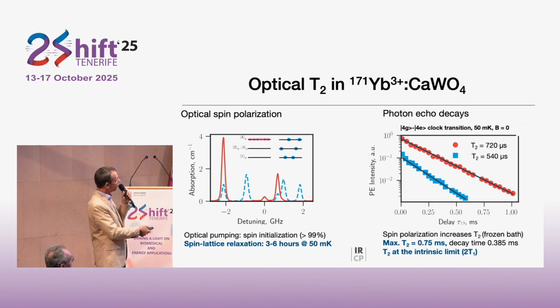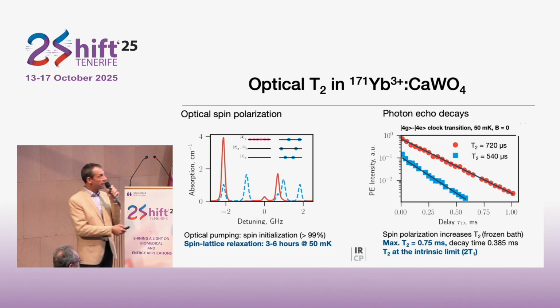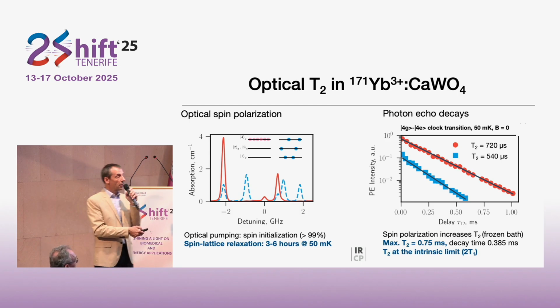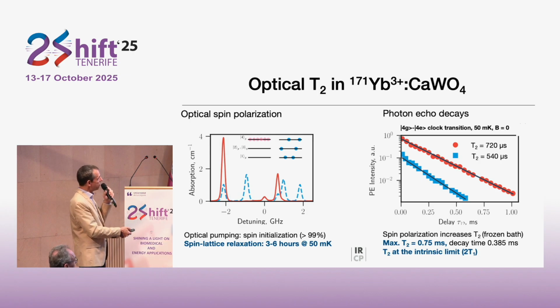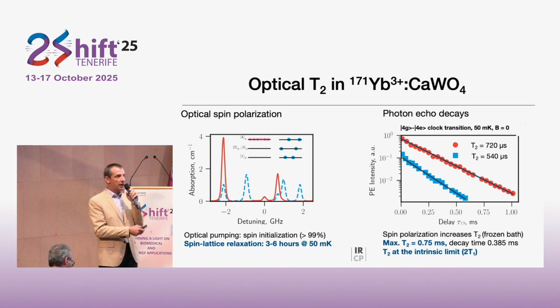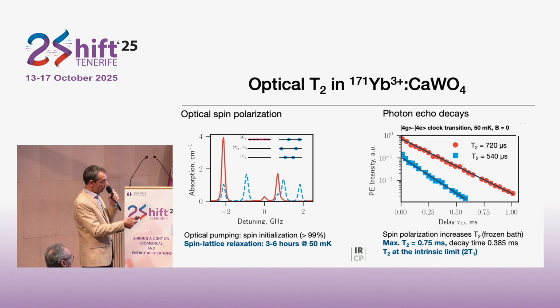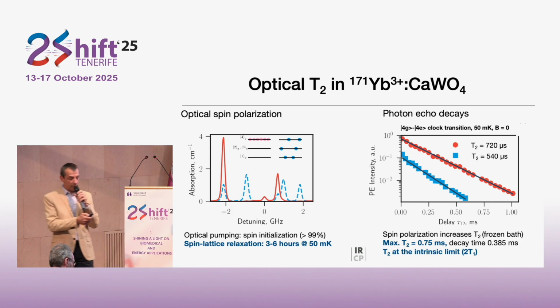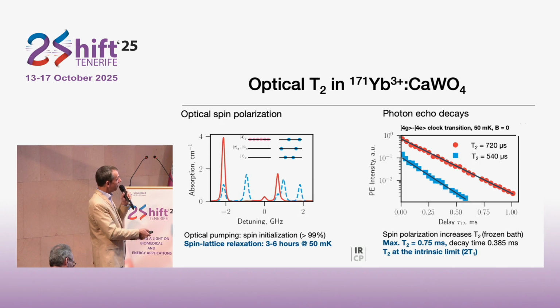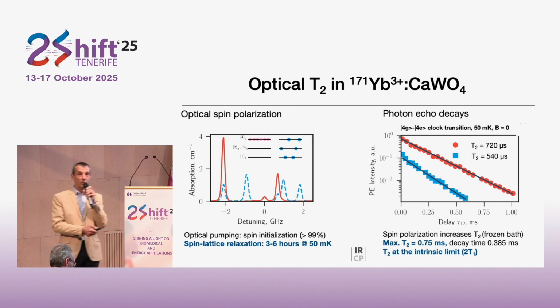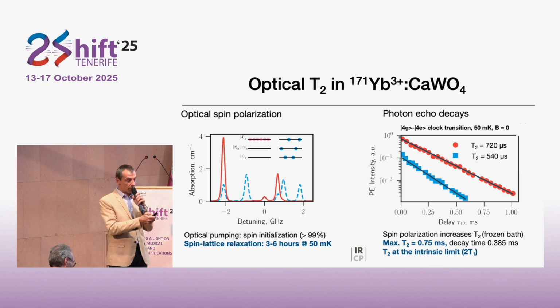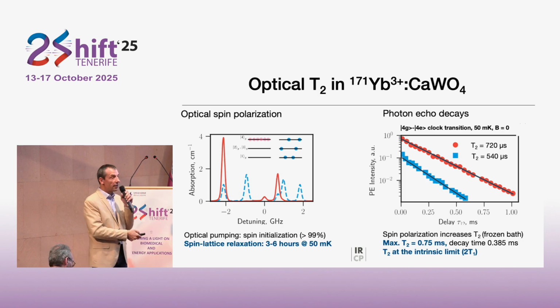Another very interesting feature here is that the longest T2 we could measure in the system is 0.75 milliseconds. And this is nice because now we can compare that to the fluorescence decay of ytterbium in this material. And this fluorescence decay is 0.385 millisecond. And it means that we are in a situation where this quantum state lifetime is actually at the intrinsic limit of the material, which is given by twice the value of the excited state lifetime, which is called T1. So T2 is nearly equal to 2T1.